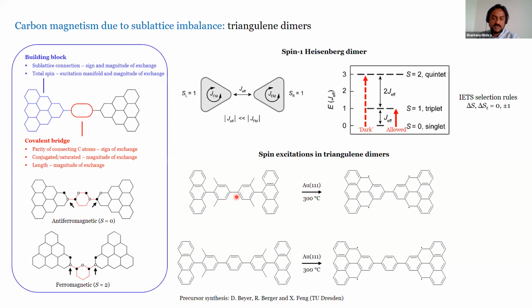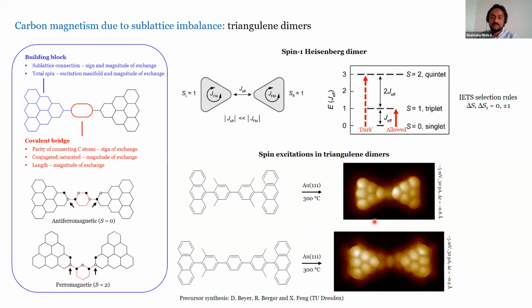In one case, they should be connected directly at their minority sublattice sites, and in the other case, they should be separated by a benzenoid ring. And when you anneal these precursors, they should give these products, and indeed that's what happens. So you have these two triangulene dimers now directly connected and separated via a phenyl spacer. We detect again the singly occupied orbitals, which is our point number 1 for detecting magnetism.